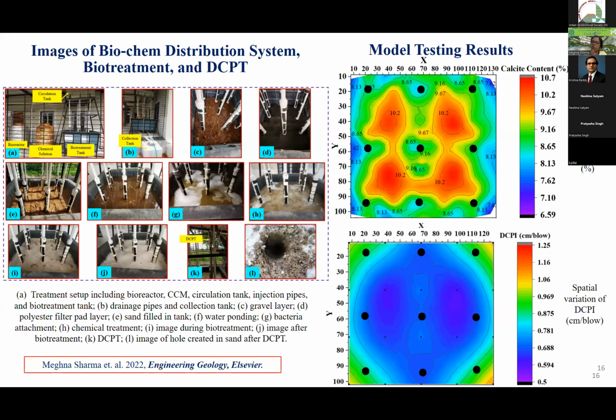Along the depth, uniformity was achieved, though the central and near-central locations get the solution from the nearest 4 injection points. That is why the amount of calcite precipitation was higher there. So we concluded that the spacing of injection pipes can be increased to achieve uniformity in calcite precipitation horizontally too. Otherwise, a significant amount of calcite precipitation was achieved throughout the depth.